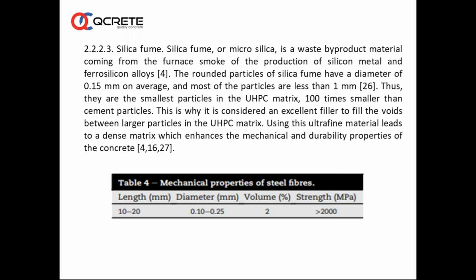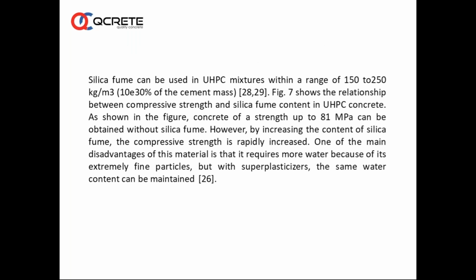So microsilica, because of its shape and size, acts as a filler. Also, it reacts with the other hydration products, making durable, high strength and extraordinary concrete as the amount of microsilica goes up in the matrix. So silica fume can be used in UHPC mixtures within a range of 150 to 250 kg, which is huge compared to a conventional concrete. In conventional concrete, we are all aware microsilica is used between 5 to maximum 6 or 7% normally. So here it is used between 10 to 30%.